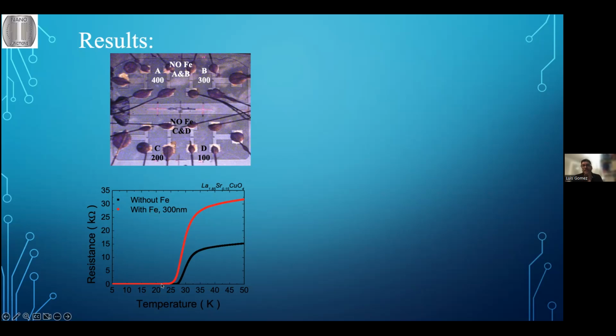temperature. So somehow adding the iron to that bridge made of lanthanum, the doping in this case is the optimally doped strontium sample. So there is 0.15 atoms of strontium in the sample. By adding the iron, we will increase that resistance that is observed before the transition. And then when it's fully superconducting, of course we have zero resistance.